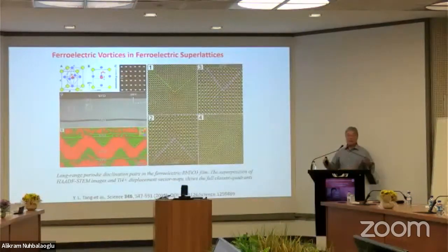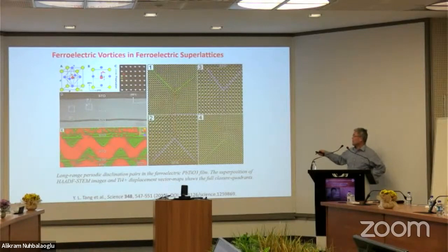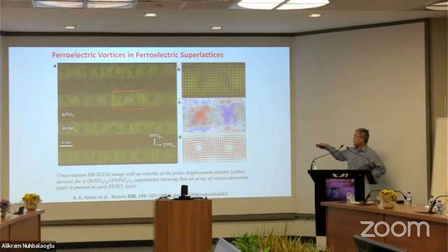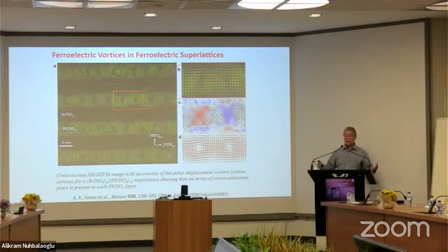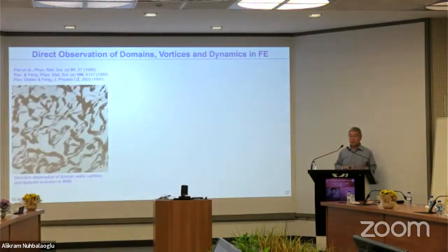And after this was observed, many people in the ferroelectric research field became interested in creating and manipulating this kind of closure structure. These are two examples. One is from the Institute of Metal Research in the Chinese Academy of Sciences. They found this kind of vortex and anti-vortices in the superlattices of strongly strained and negatively strained layers. So this is very similar to the closure structure we've seen before. And also, my student Chris Nelson, when he finished, he developed this method for mapping, and then joined Berkeley, and continued to study and found this very nice vortex and anti-vortex. Vortices and anti-vortices already in the very thin layer of the superlattice structure. After this, there are a lot of other structures, skyrmions, and edge domains, and nanoscale